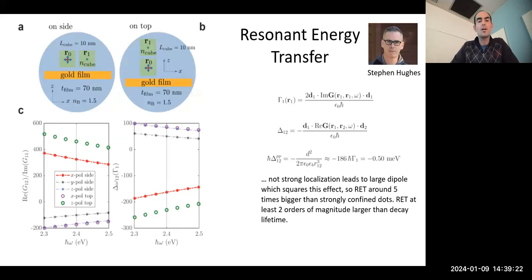Interestingly, for the geometry we have here, for this type of perovskite quantum dot, resonance energy transfer turns out to be the strongest process by far, which is surprising, because other types of quantum dots wouldn't show this level of splitting or energy shift from this process. This is because of the type of coupling - their dipole moment is very large.